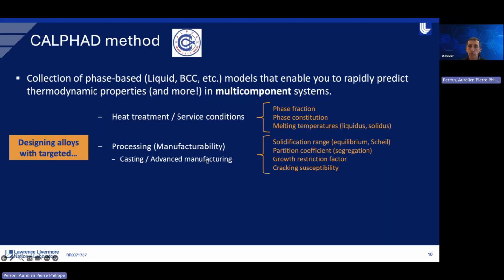So how do you do that? You can also calculate a lot of properties that are related to solidification. At equilibrium or under non-equilibrium conditions, you can calculate, like, partition coefficient that will give you an idea about the segregation of your alloys. Cracking susceptibility: there are a lot of models to estimate if your alloy will crack or not during solidification.